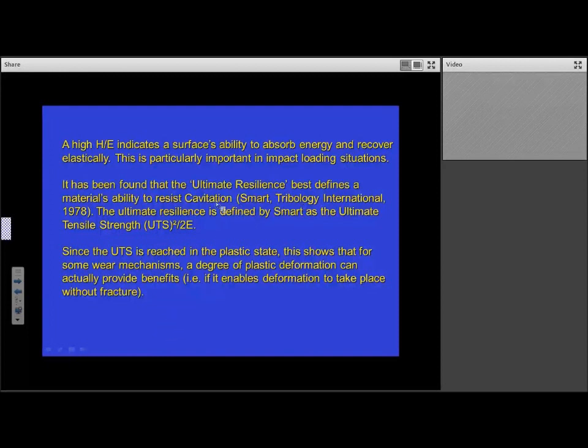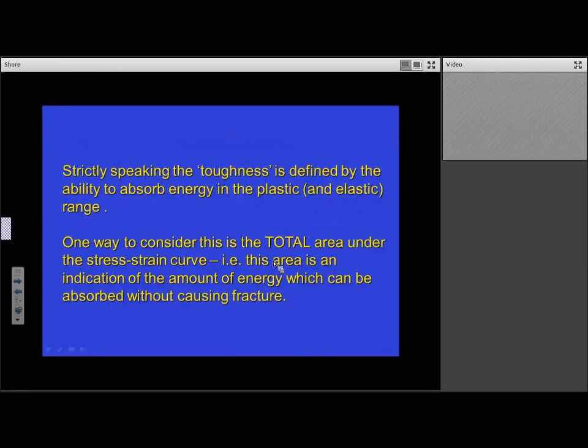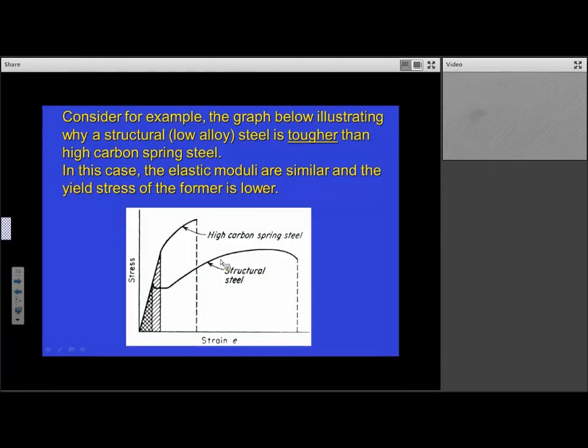And a guy called Smart said that for cavitation, which is one particular kind of impact, what we should think about is not Y squared over 2E or H squared over 2E, but the UTS squared over 2E. And that's in recognition of the UTS being reached in the plastic state, and therefore some ability to absorb energy can occur plastically. You should think about the toughness being defined by the total area under the stress strain curve, not just the elastic part, the elastic resilience. So we know, for example, that a mild steel, a structural steel, is tougher than, for example, a high carbon spring steel. This might have a higher elastic resilience, but this is tougher. This is more able to absorb impact. So now what we're getting into is that it could even be a good thing for a tribological surface to have some ductility. And that would go really right against the thoughts of those early tribology theorists.